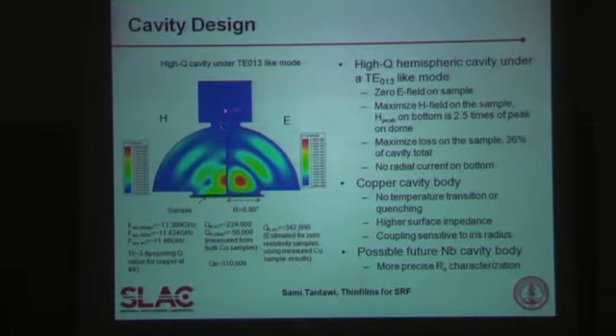And this cavity structure basically is a TE013 like mode with 3 lobes in the radial direction. It's actually very much a spherical cavity. It's almost exactly spherical except with this opening and this small protrusion, so we can put the flat sample. And the reason for this spherical structure is that it makes the field on the sample much, much higher than the field on the surface of the cavity. And it also makes the part that's responsible for the quality factor of the cavity much more dependent on the sample than the rest of the cavity, which is made essentially out of copper. That's quite different than most other cavities.